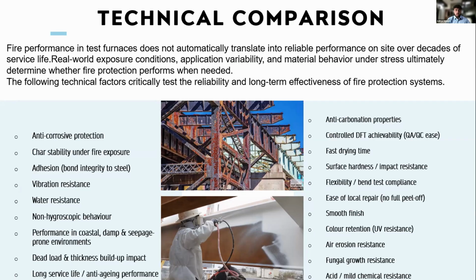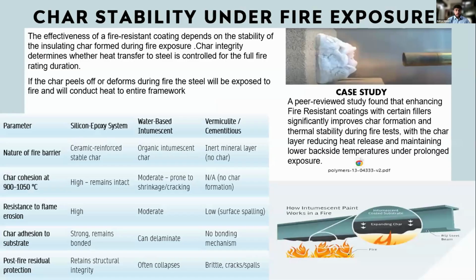So there's anti-corrosive protection, char stability. We'll dig deeper into that. So firstly, we come to the char stability under fire exposure. As I just said, intumescent coatings have a tendency to expand up to 50 to 70 times more. So if the char falls off under fire exposure, then the steel is exposed to fire, and steel is conductive in nature. So even if you lose a patch of that char, it will conduct the heat through all the framework, and the point of doing that coating will fail.